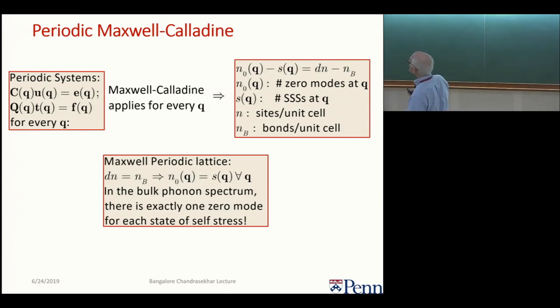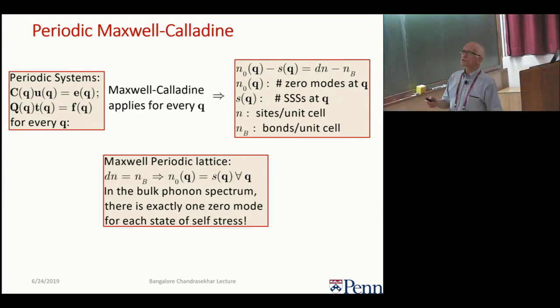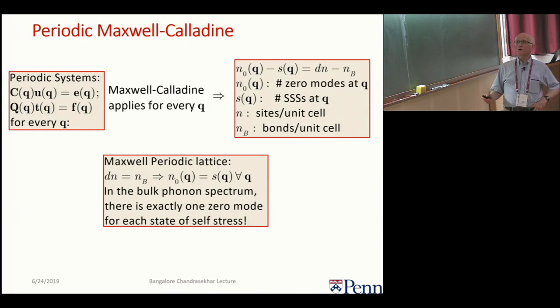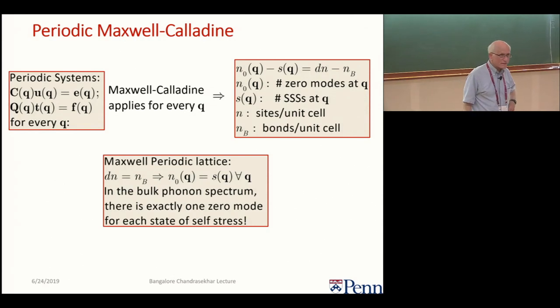So for each Q, I have the number of zero modes at wave number Q minus the number of states of self-stress at wave number Q is equal to the number of degrees of freedom in a unit cell minus the number of bonds in the unit cell. And we can now apply the theorem that follows from the fact that I can write that there is a submatrix of dimension little dn cross dn, such that C operating on U of Q gives me E of Q, et cetera. So the Maxwell lattices we're looking at, we've chosen so that dn is equal to nb, which means that the number of zero modes always has to equal the number of states of self-stress. And that immediately tells us a lot about the spectrum of the phonons.